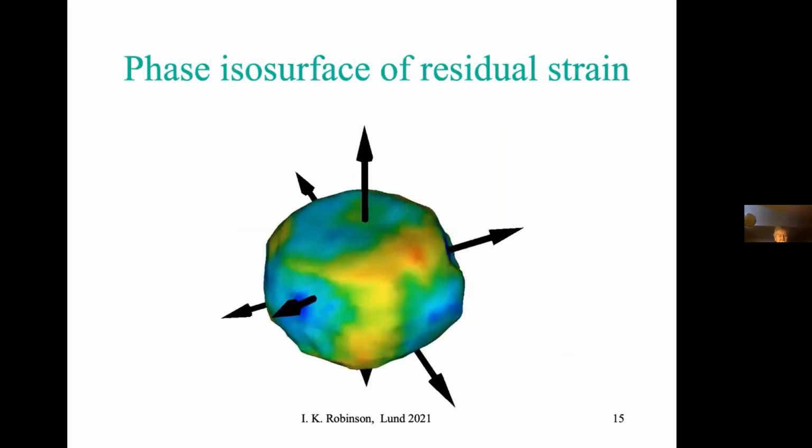And then the other part of it, which is actually very important for the science, is that the images are complex. In general, unless the diffraction pattern happens to be locally centrosymmetric, there will always be some asymmetry of the diffraction, which leads to an image which is generally complex. And the interpretation usually is that the phase of the image that comes out, which is used here to color the boundary of the isosurface of the gold crystal, is an indication of the deformation of the crystal.